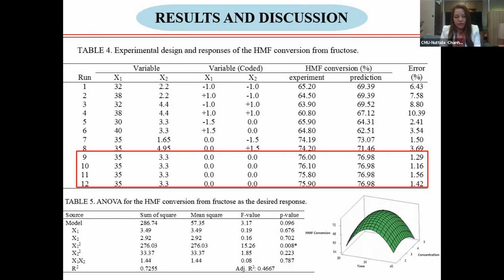The result showed the HMF conversion from fructose ranged from 60.8 to 76.1% depending on the experimental condition. ANOVA was applied to the model. It showed that the process parameters are significant for the HMF conversion, and the R squared and adjusted R squared for the conversion model were 0.7255 and 0.4667 respectively.